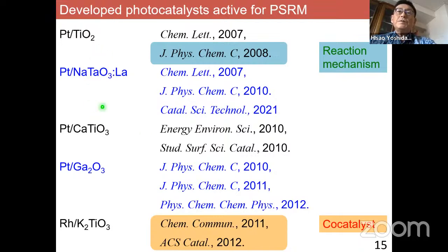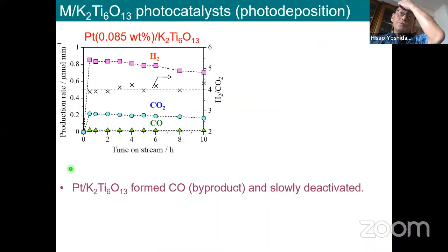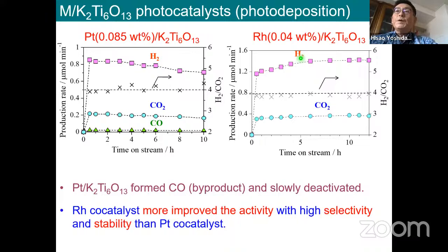The second, I want to introduce the co-catalyst effect. For example, in these reactions, we usually use platinum. So I also used platinum for the next photocatalyst, potassium titanate. In this case, the reaction was promoted, however, it decreased a little bit with time, and the byproduct carbon monoxide was also formed. Then we changed the co-catalyst to rhodium. The reaction rate became higher, and the byproduct was not observed.